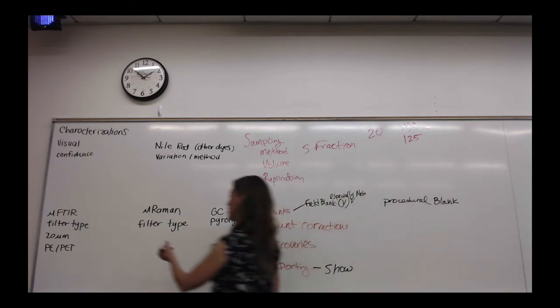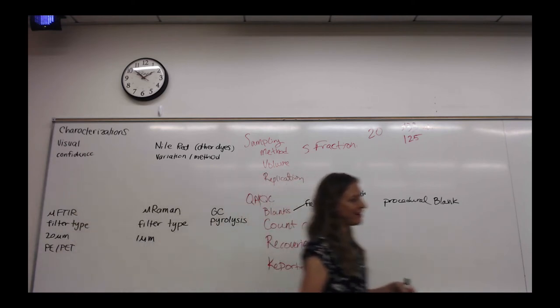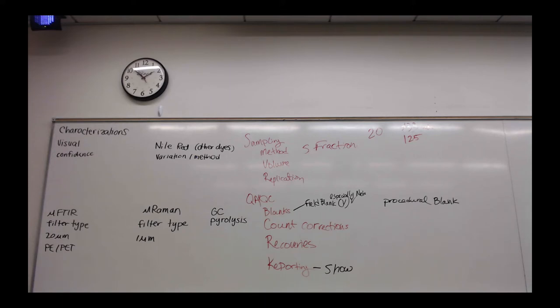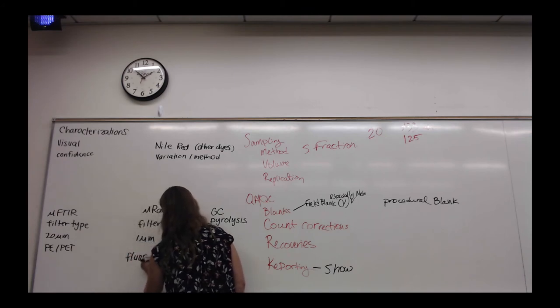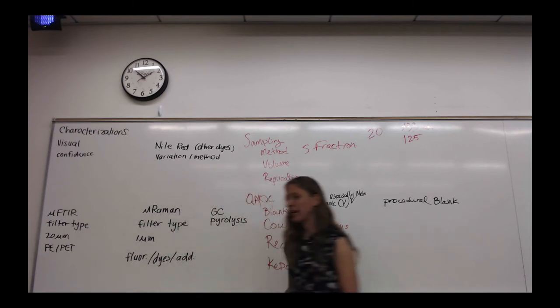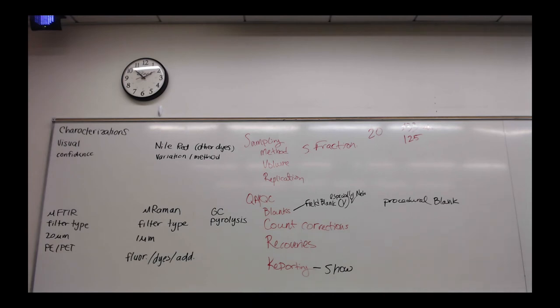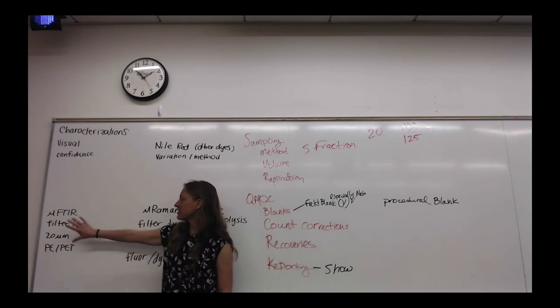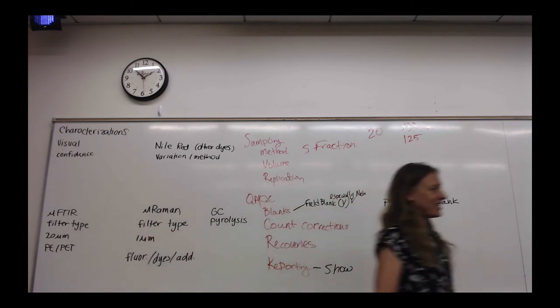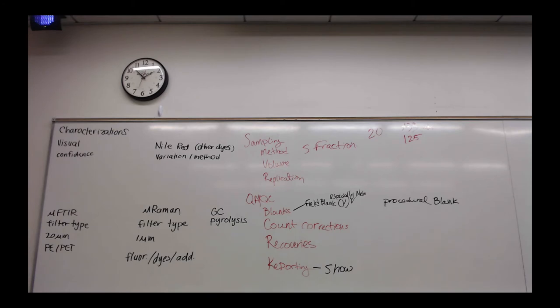The other thing with Raman is you can go down, in theory, to 1 micron. And so that's helpful. But it is very strongly influenced by fluorescence. I guess I should put that up there. And dyes and other additives can be very damaging to your signal. So there's things to, those are things, just considerations. Also, and I think I feel like we noticed this with our data, Raman is the signal for PVC is actually much stronger. And so what's interesting is that things, signals that are weak here are strong here and vice versa. And so in a way, they can be complementary, but I don't know that we'd want to suggest both methods for samples, because that would be quite tedious and not necessary. But scientifically, they do offer different types of information.